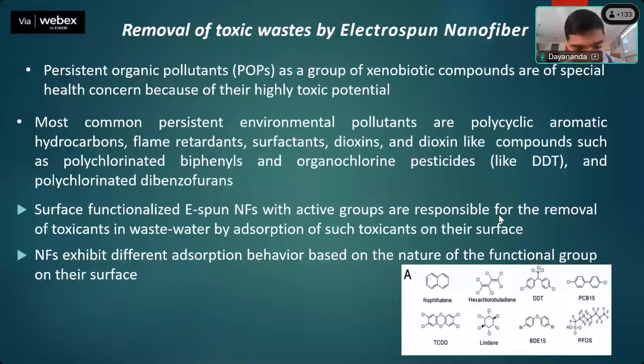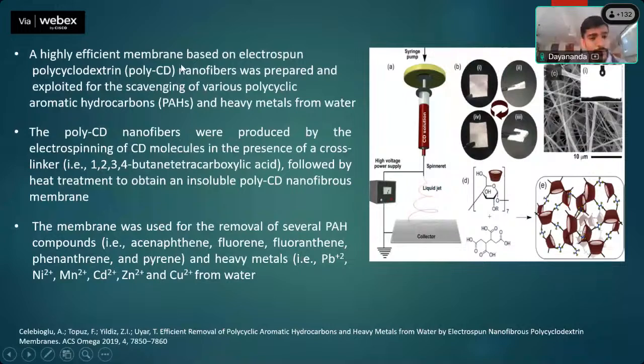This is one strategy that was published - they took cyclodextrin and mixed it with 1,2,3,4-butane tetracarboxylic acid, and then once the nanofiber mat was obtained, it was subjected to heat treatment to form an insoluble poly-CD nanofibrous membrane. This membrane was tested with several impurities including heavy metals, and it was found effective in removing heavy metals like lead and copper.